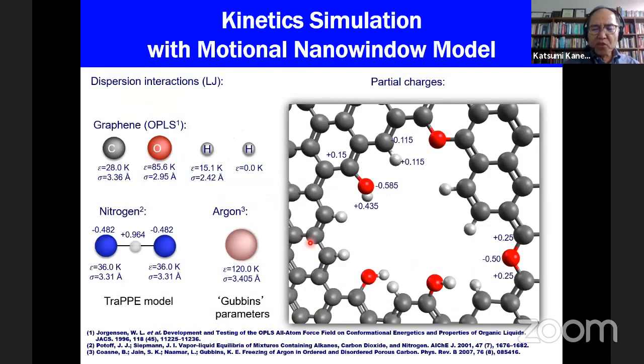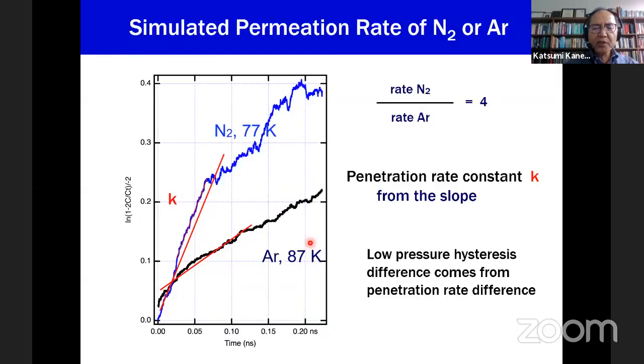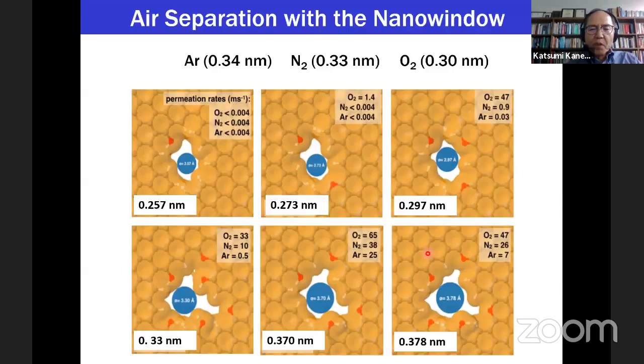But here we just applied molecular dynamics, then evaluated the permeation rate, the penetration rate through the window. Here we just examine six sizes of the nano windows from 0.26 to 0.38 nanometer.